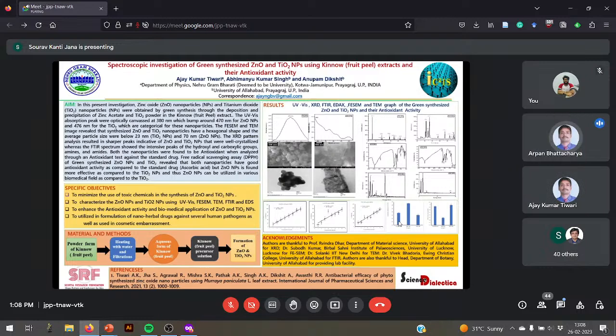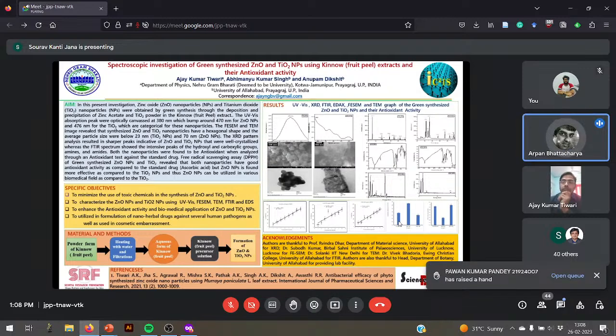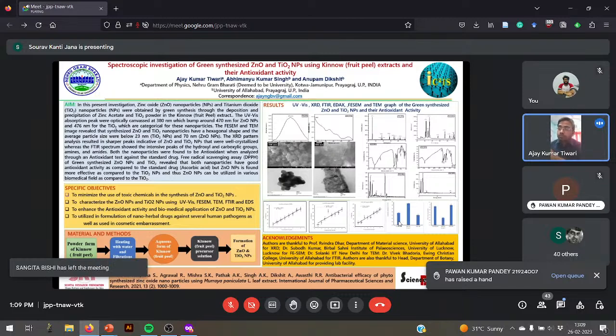Thank you. So what was the final size you obtained? I mean, what was the change in size of TiO2? Because you have already used TiO2 powder in the precursor, and you found TiO2 nanoparticles. What was the size change? Earlier it was about to. Even I have not checked. Mostly we have seen one above 100. Here its size is reduced due to the reaction. Have you checked through your data? No, sir. In literature I have seen. Here I have done only this one.